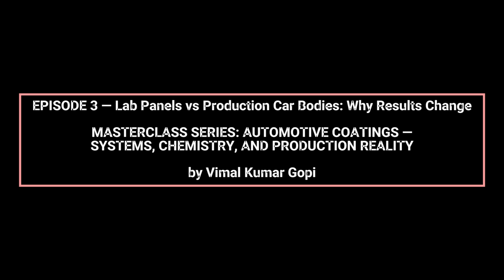Thermal mass and orientation further contribute to observed differences. Production panels are larger and more massive than lab coupons, which affects heat transfer during flash-off and curing cycles. Similarly, the orientation of the panel, vertical, horizontal, or inclined, modulates flow behavior and solvent evaporation. These factors influence the final metallic particle orientation, gloss development, and defect incidence, especially in solvent-based primers, basecoats, and clearcoats.